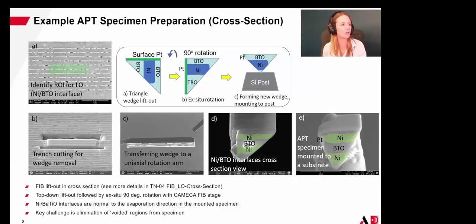But just to give you a quick overview, what we do here is pull a wedge, and then we mount this to a transfer arm. This is in the FIB stages that we offer for sale here at CAMECA. And that will allow us to rotate this at 90 degrees, recut the wedge so that we have the interface between our electrode and our ceramic within each mounted wedge.